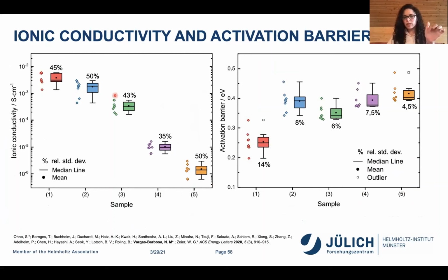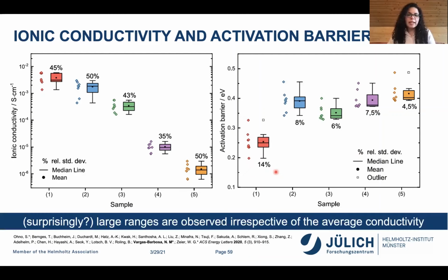And so look at these ranges, irrespective of the absolute magnitude of the electrolyte, we have extremely large ranges. And we were actually surprised about this. Some of our colleagues said, oh, this is to be expected because everybody has a different setup. So everybody measures things slightly differently. Well, but then, if it's a setup thing, then we must be able to find a parameter that describes this spread, right? And it's not exclusive to the ionic conductivity, but it's also reflected in the activation barrier, even though the relative standard deviations are not as bad.